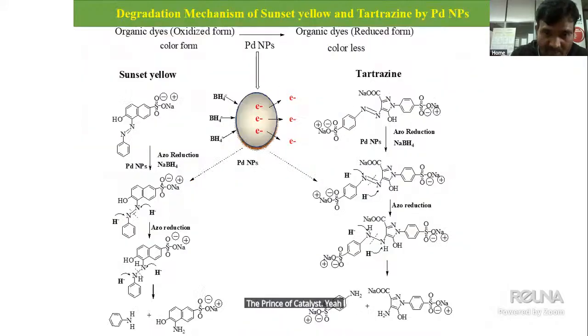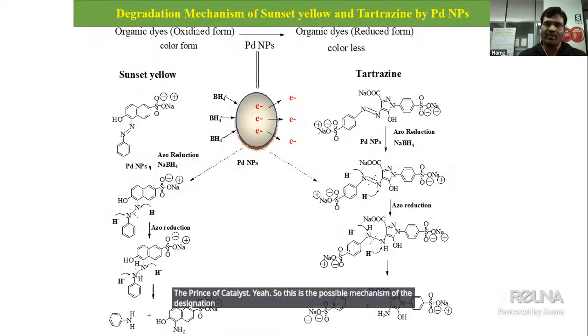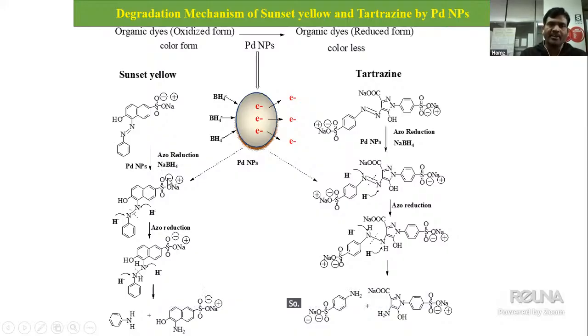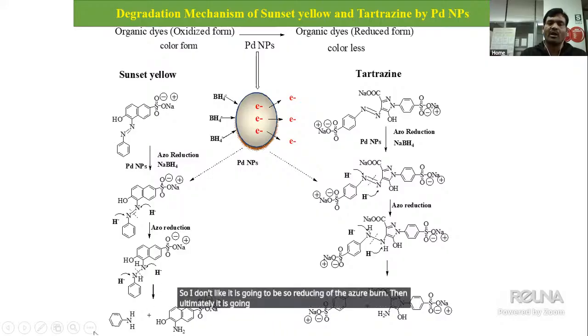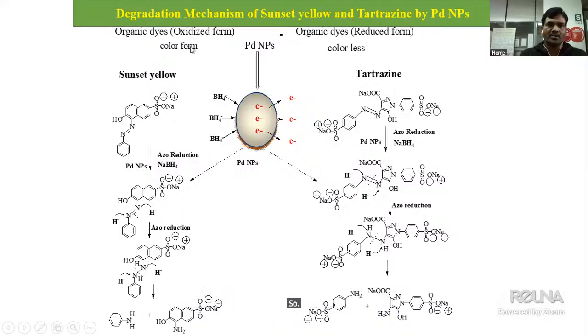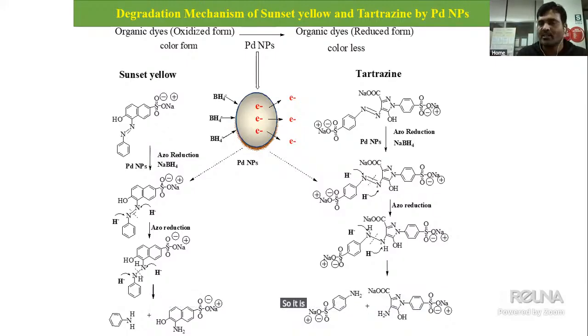So this is the possible mechanism of the dye degradation. In the presence of sodium borohydride, electrons are released. Then the electrons capture the hydride ion, which leads to the azo reduction reaction. The hydride ion reduces the azo bond. Then ultimately smaller entities are formed. The dyes go from oxidized form to reduced form. It is a reduction reaction, the azo bond breaks, and a smaller entity is formed, which is less toxic and not toxic to the environment.